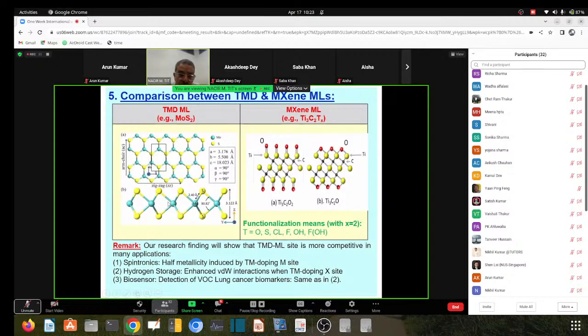If you look from side view, you find it like this. So you have the atomic monolayer, and it's surrounded top and bottom by the chalcogenide monolayers. Whereas in the MXene, the number of metallic monolayers is more than the chalcogenide, or maybe not chalcogenide, it has other layers which are either carbon or nitrogen. So too many MXenes have been grown, with different thicknesses. The thinnest one may be Ti2C, plus the passivation layer, which can be oxygen or other passivation layers.